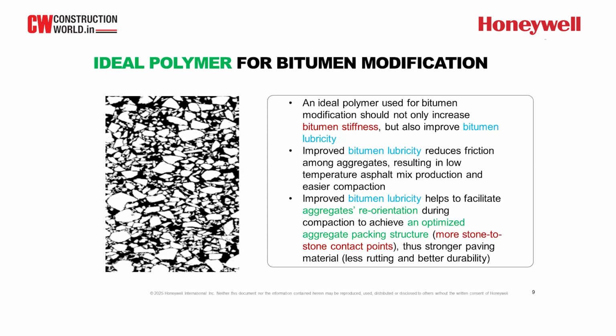Or to ask it another way, what is the ideal polymer for bitumen modification? In our opinion, the ideal polymer used to modify the bitumen should not only increase the bitumen stiffness, or the PG grade or the viscosity, you can name it, and the modulus at high temperature, right? So warm climate temperature, because it will give us better rutting resistance. It should also improve bitumen's lubricity, because we just discussed bitumen acts as both a lubricant and a binder. We need the lubricity from the polymer.